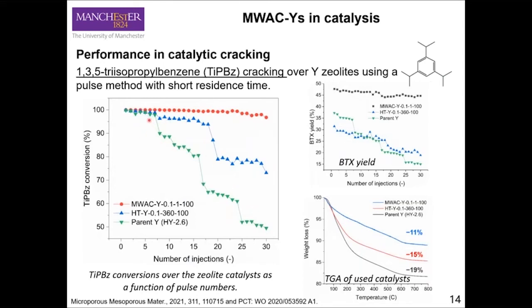For the materials prepared using conventional methods, it's quite effective initially, but in the end they deactivate. But the one we prepared using the microwave method is much more effective and resists deactivation, which can also be seen from the yield of BTX: benzene, toluene, and xylene. The microwave-prepared material is much more selective to BTX, which means it can effectively crack and remove all those branches from the model compound. The TGA results also show that the anti-coking performance of the materials prepared by the microwave method is much better.